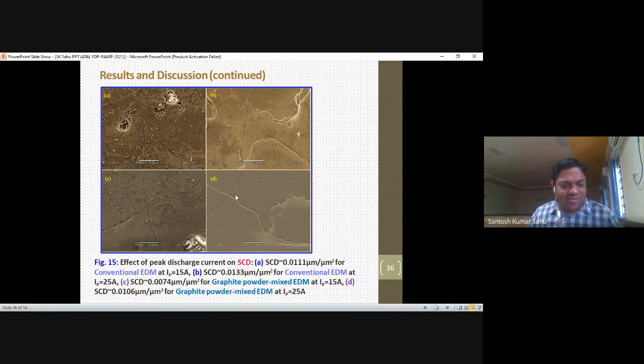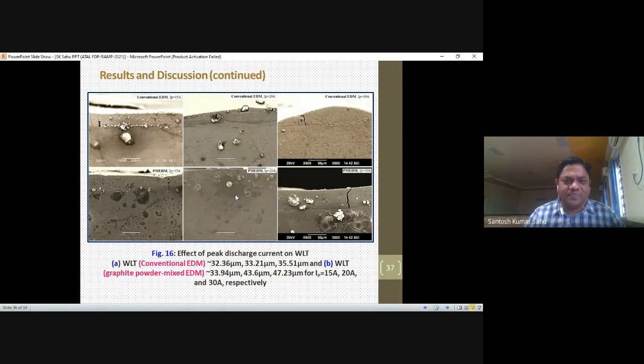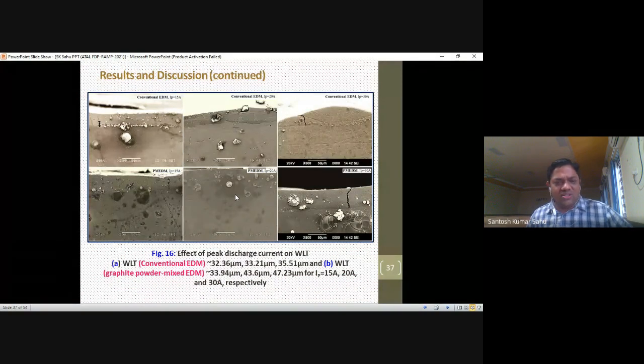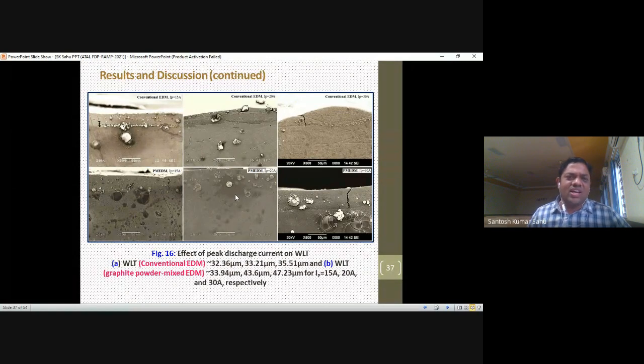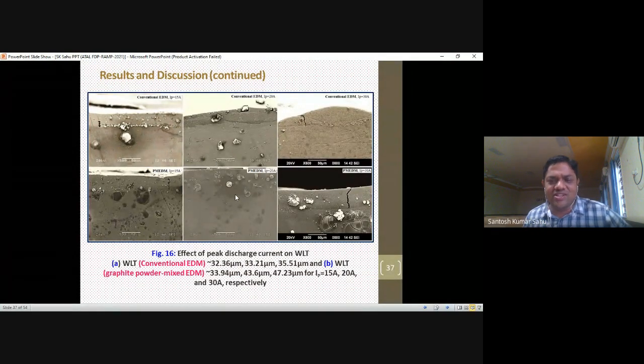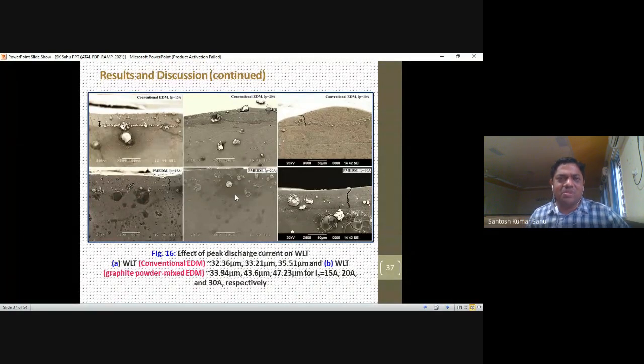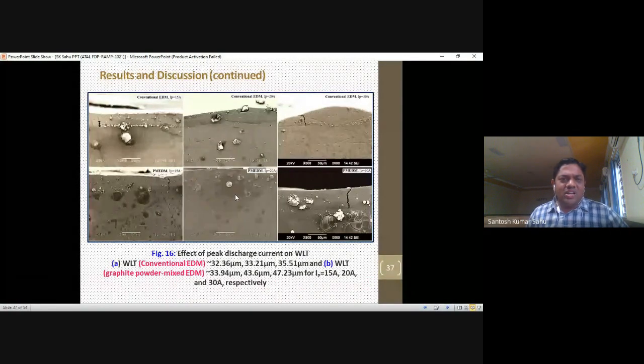And finally, you have to see that the surface cracking to a lesser extent has contributed to a superior surface finish. Again, we have to see in the figure the effect of the peak discharge current on the white layer. In conventional EDM, you have to measure the white layer thickness. If the white layer thickness increases, it becomes a limitation of our machining process. It should be minimized. But here they have taken a conventional one without powder mix.